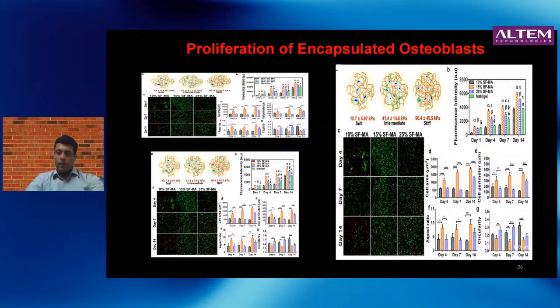But since we were interested in bone tissue engineering, what we did was to take MC3T3 pre-osteoblasts, and we encapsulated them in scaffolds or these hydrogels, which were of 10, 15, and 25% polymer, and which meant that the stiffness varied from about 10 kilopascals to about 100 kilopascals. And what you find here is that the cells were viable in all of them. However, the cells seem to grow the best in the 15% silk fibroin gel of intermediate stiffness, not the very soft gels and not the very stiff gels. It was the intermediate stiffness, about 40 kilopascals, where these cells were growing the best. And in fact, the cells were actually spreading out a lot in these hydrogels over time.